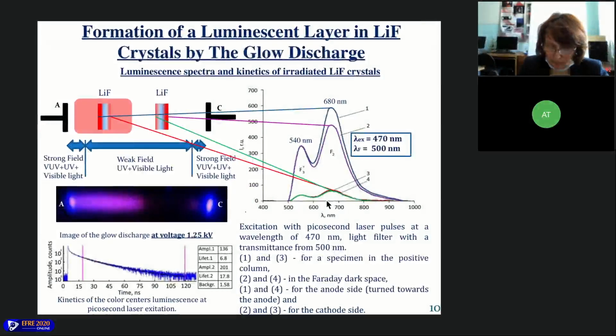On the slide, you can see the luminescence spectra and kinetics of irradiated lithium fluoride crystals obtained using a microtime laser confocal scanning luminescence microscope equipped with an Ocean Optics spectrometer. Luminescence measurement results show that two major types of color centers were created in lithium fluoride crystals, namely F3+ and F2, with luminescence bands at 540 nanometers and 680 nanometers, and decay time constants of 6.8 nanoseconds and 17.8 nanoseconds.